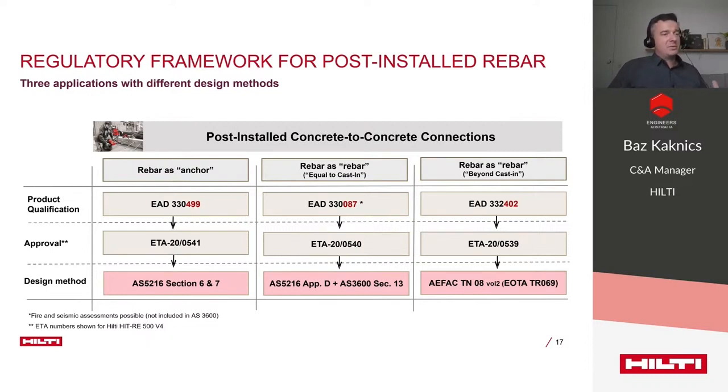The chemical here will require a special qualification report, which is based on the assessment document ending with 087. This method doesn't utilize the tensile capacity of the base, and the tensile stresses will have to be transferred either via lap splicing with an existing bar, or the area of the fixings must be under constant compression so as to rule out the possibility of a concrete cone failure.